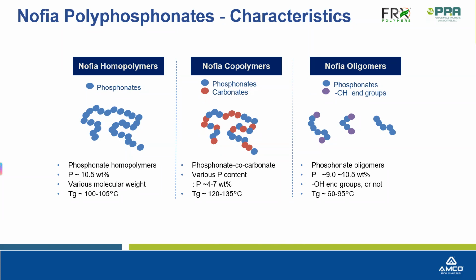In the FRX product line, there are 3 types of materials, all more or less the same chemistry, but different forms. The Nofia homopolymers have about 10.5% phosphorus in them, various molecular weights, and a Tg of 105 degrees C. The Nofia copolymers are copolymers of phosphonate and carbonate, so they look like polycarbonate and perform similarly to polycarbonate in some of the applications, whether they're used as a copolymer or as part of a blend or an additive in another polymer, and polycarbonate in particular is our main polymer we go into with these copolymers.